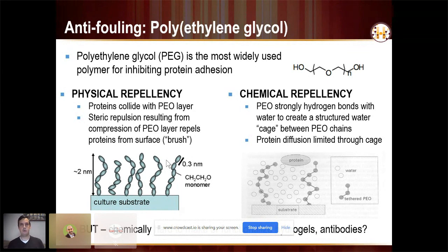But there's a key problem with this, or I wouldn't say problem, but limitation, and that is this is a step growth polymer, so there's only two functional groups in it, one at each chain end. So if I'm trying to make a hydrogel, I need to cross-link this. I basically need to use up virtually every functional group in the material in order to make a hydrogel. You can make star polymers and fancier morphologies to get around this, and people have done this with a lot of effectiveness, but it's more synthetically demanding.